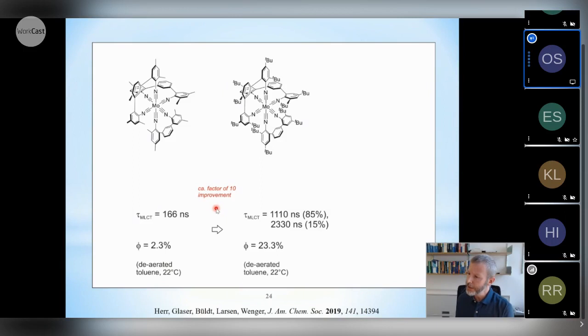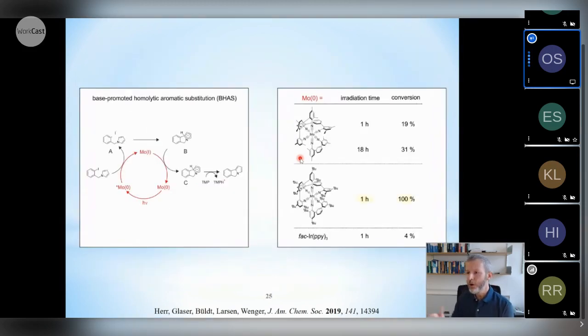Here this worked rather beautifully in the PhD thesis of Patrick Herr and Felix Glaser, who showed jointly that the initial figures of merit here, MLCT lifetimes and photoluminescence quantum yield, can be boosted by nearly a factor of 10 here, simply by introducing these sterically more demanding ligands. And in the context of catalysis, which is in focus today here, this also had a significant impact here.